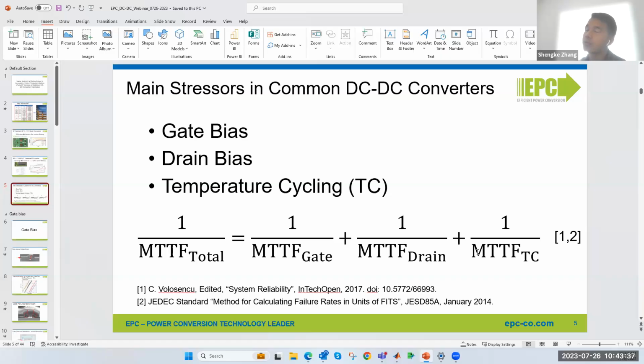So this is showing the approach of how we try to address the reliability issues. When we see something that is a very significant term in the denominator, which was temperature cycling in the beginning, that's why we address it by using underfill material. So far, the total mean time to fail, or the fail rate in the field, is consistent with what we have studied based on our reliability testing results, which is very low.